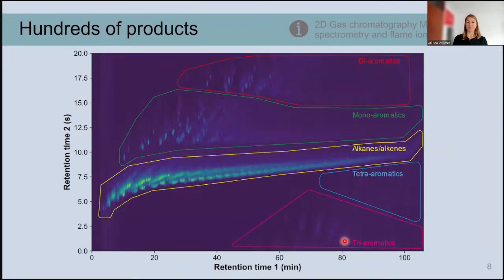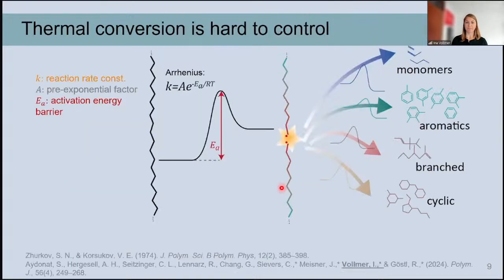And so what happens if you do this high temperature treatment during pyrolysis? You do that with exclusion of air and oxygen so that the plastic is not burning, but pyrolyzing instead. You get a product which is very mixed. So this is a 2D GCMS chromatogram, and every little blob in this graph is a different chemical species. So there are thousands of different molecules formed, and this is why this has to go to the chemical industry again to make monomers out of it, and it cannot be used directly to make plastics.